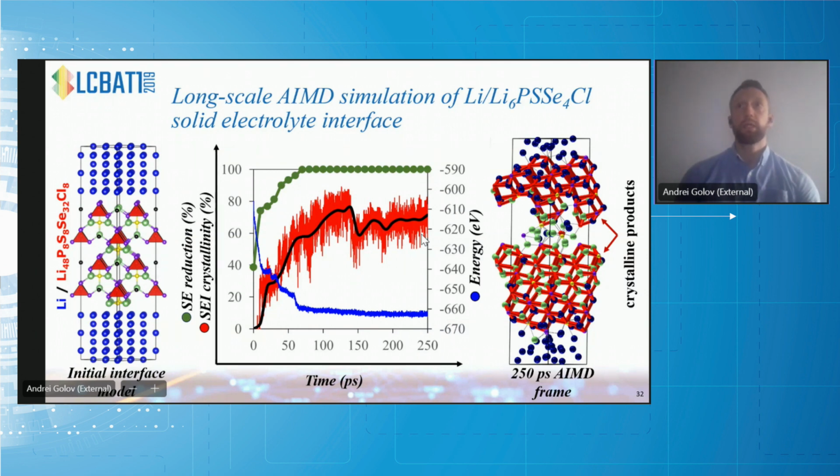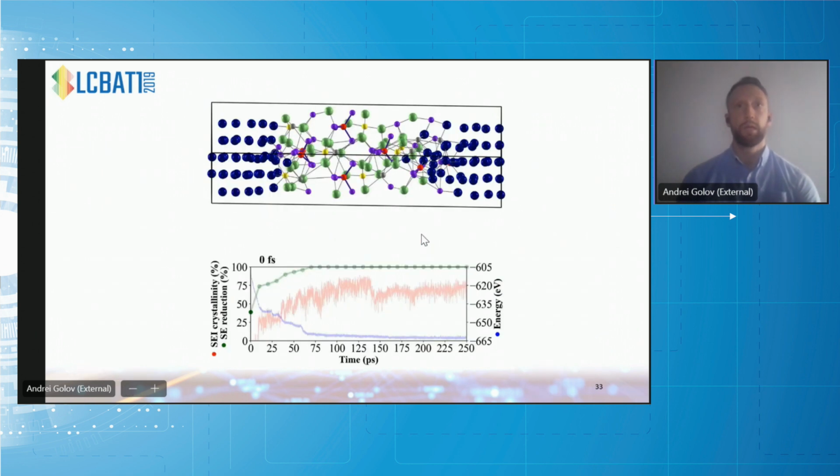And additionally, to get information about the crystal structure of the solid electrolyte interface, we carried out a long-scale MD simulation with the selenium argyrodite structure, which exhibits a much higher reaction rate. And at the end of the simulation, we were able to observe the formation of the crystalline product.